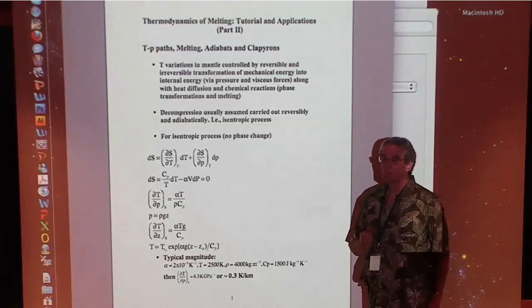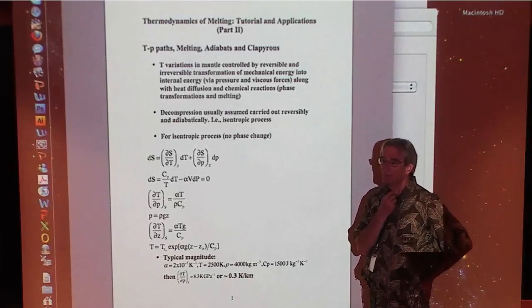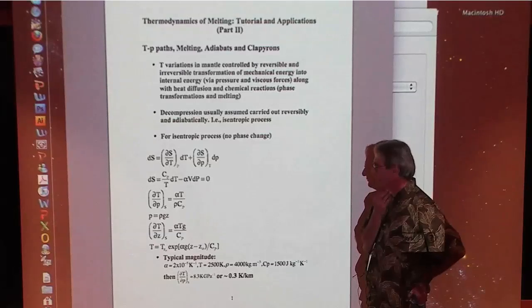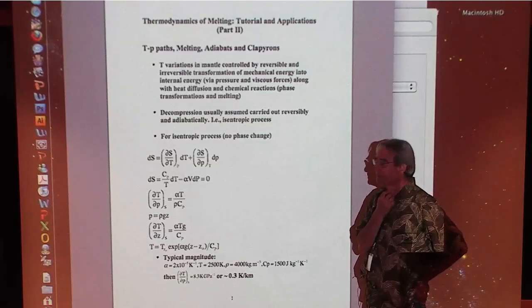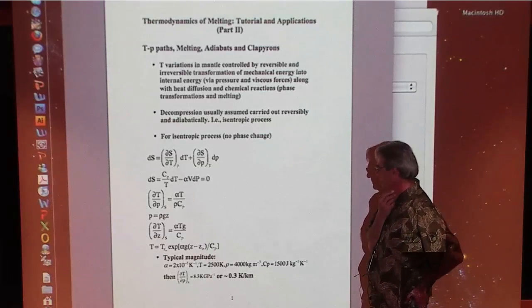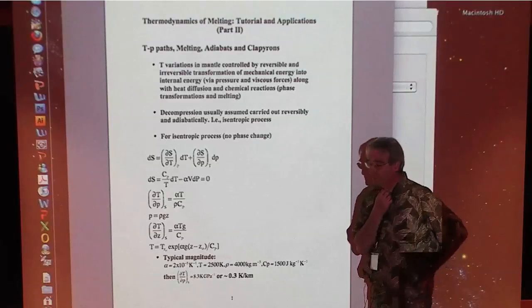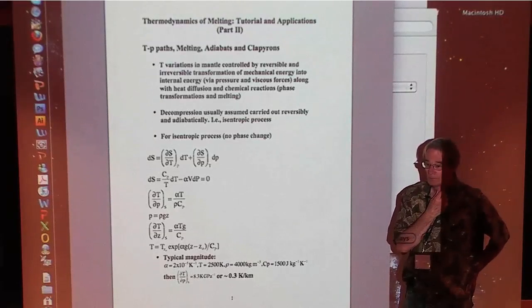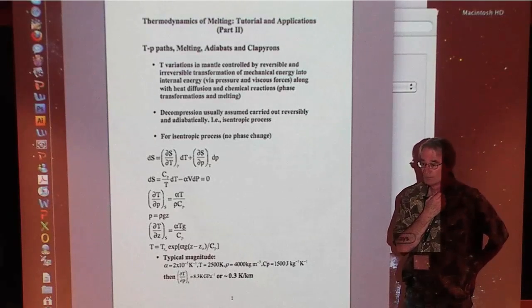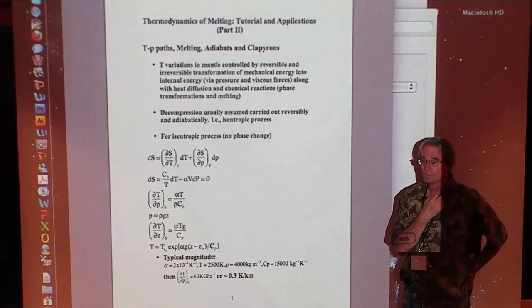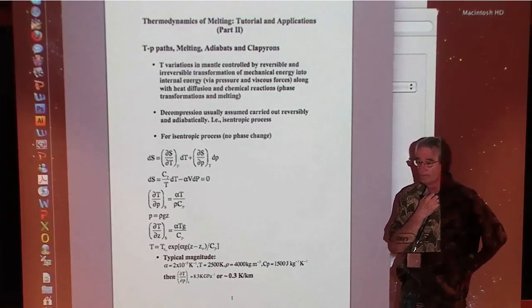So this is the difference between low pressure people and high pressure people. Yeah. The Grüneisen parameter is about equal to 1. So that's why we keep talking about Grüneisen parameters, is that we can put in a factor of 1 there, and then the adiabatic gradient is the ratio of the temperature to the bulk modulus, both of which we know, as opposed to all these messy thermodynamic parameters like heat capacity and thermal expansion. Okay. So that's the real utility of the Grüneisen parameter.